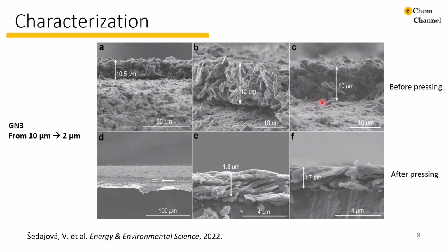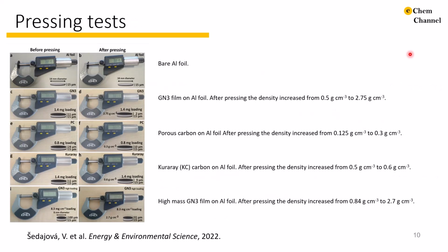Here, from the thickness measurements which we performed using SEM and also a digital micrometer, we optimized the pressing test and also the paste composition to consistently reach 2.7 to 2.8 gram per cubic centimeter, compared to the already mentioned around 0.5 gram per cubic centimeter before pressing. Here is the overview of all of the pressing tests we are showing in the paper. So we are showing the bare aluminum foil, the GN3 material on aluminum foil, both of the commercially available carbons, and then the high mass loading.